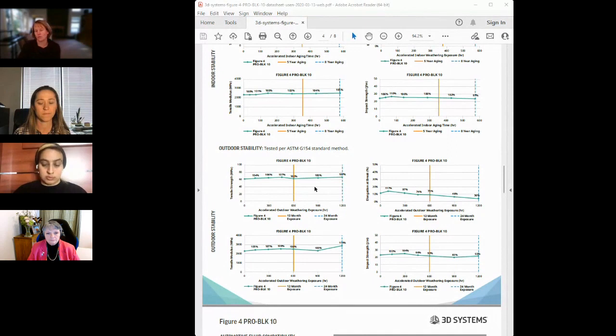year of real exposure. And you can see for this material, several of the metrics are stable, but we do see some degradation in the elongation, which tends to be the most sensitive metric, and which would indicate, depending on how long you're going to use this in some sort of outdoor environment, you may see some degradation.